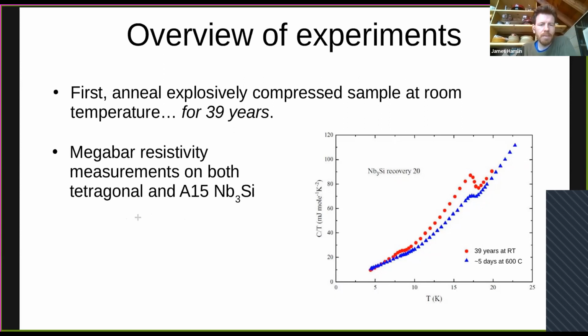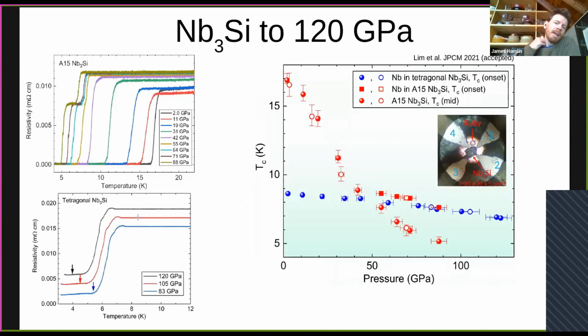We then did some megabar resistivity measurements, both on tetragonal and the A15 niobium-3 silicon phase. And so on the left here, we have resistivity measurements versus pressure on both the A15 phase, that's the one that was recovered from the explosive compression experiments, and the tetragonal phase. And the phase diagram is here on the right. And so what you can see is that the TC of the A15 phase goes down. And then we look at the TC of the niobium-3 silicon phase, and this shows basically some niobium impurities.